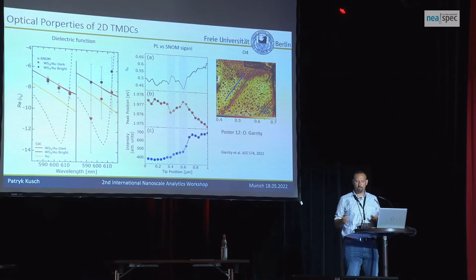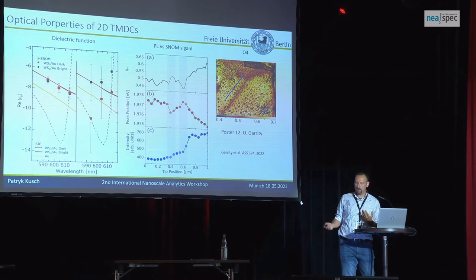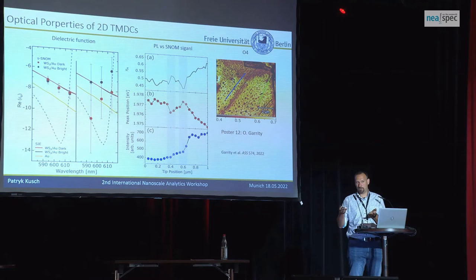With a large 2D material, I have a big spot of 3 micrometers. I put a tiny tip inside and see maybe a slightly larger signal. Is this really tip enhancement, or a focusing effect, a mirror effect? To demonstrate to at least yourself — or your supervisor — that you have the resolution to claim tip-enhanced PL, we go to graphene as a probe. We take graphene in a conventional tip-enhanced Raman setup: retract the tip out of the focus and see how the signal decreases.